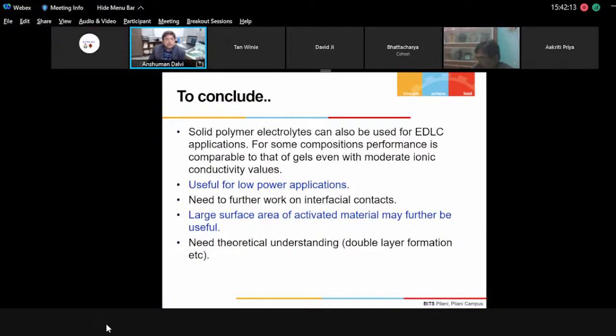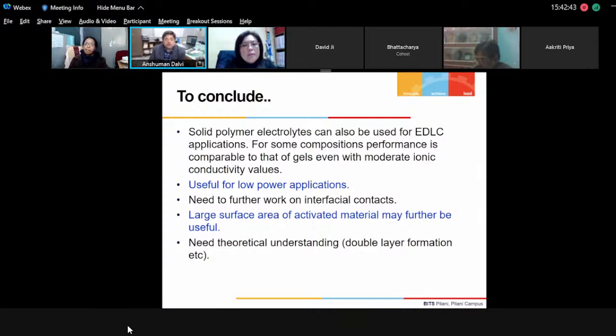So to conclude here, first of all, the solid polymer electrolytes can also be used for EDLC applications, and for some compositions the performance is comparable to those of the gels, even with moderate ionic conductivity values. And when the ionic conductivity of the solid electrolyte is higher, then in fact better results are obtained. Like the other solid state devices, these can also be used for low power devices, and one has to explore the physics behind the processes.